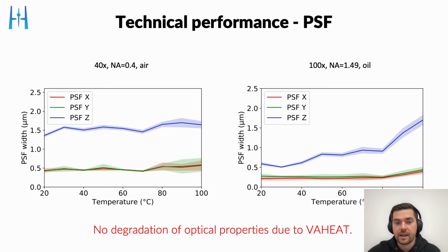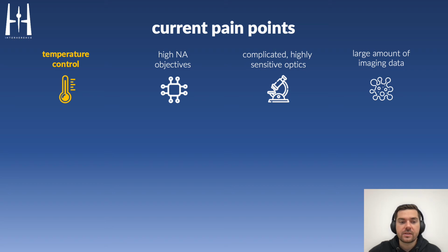Up to 80 degrees C, the point spread function in the lateral direction stays diffraction limited. Above that, it's widened slightly, but this is due to the effect of the nanoparticles that we are tracking, which start to diffuse at those temperatures. So this is so far the VAHEAT system, which tackles temperature control.